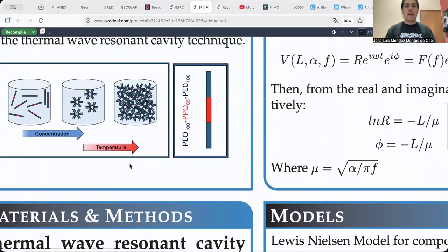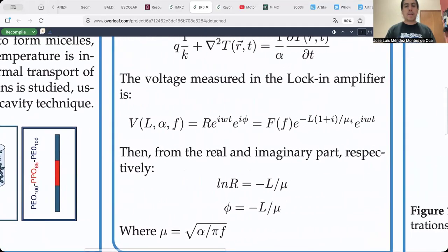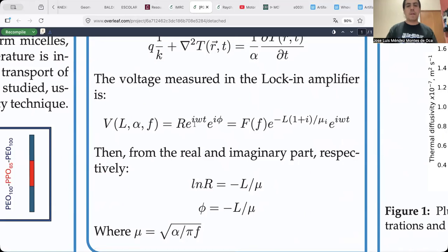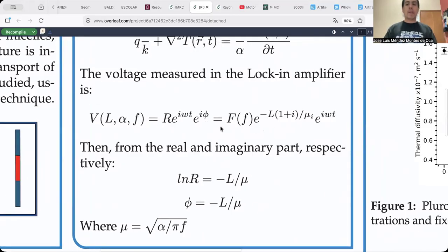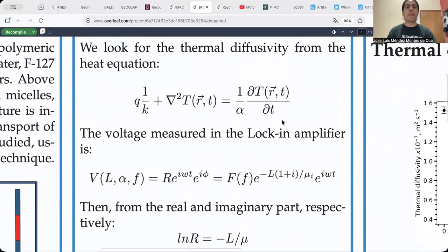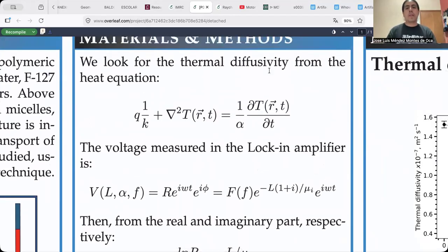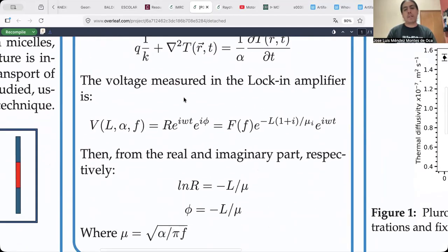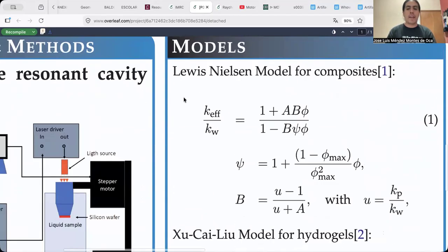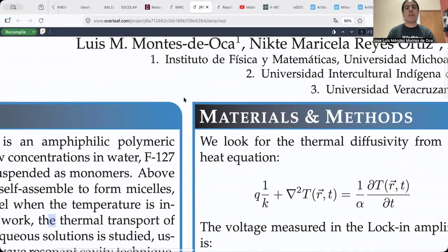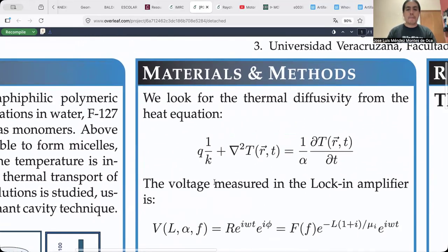With this method, a voltage signal is obtained with an amplitude R, frequency omega, and phase phi. Then this voltage signal can be related with the solution of the heat diffusivity equation in one dimension. Well, if our experimental array is well aligned and axially symmetric, the solution of this equation in one dimension only can be used.